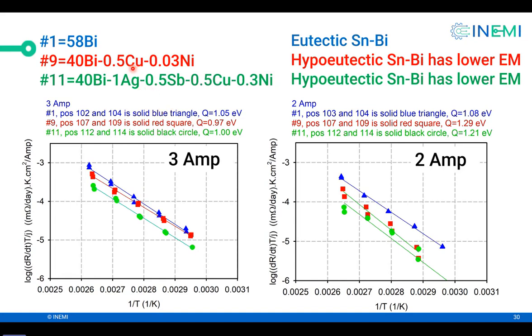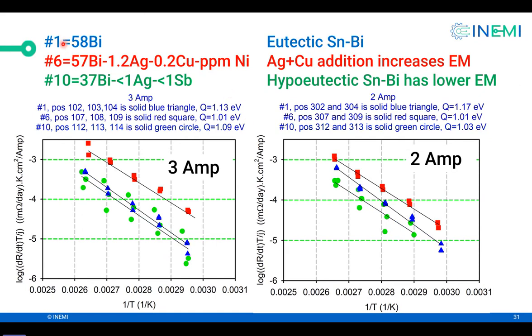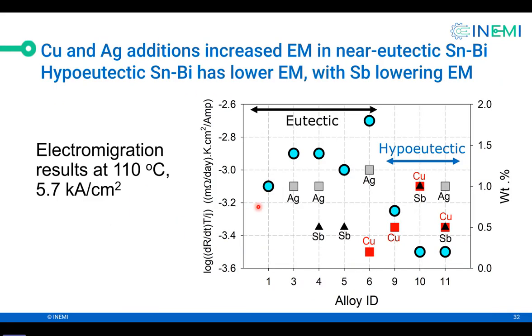And the last set of data is for, again, the eutectic compared to near eutectic with a lot of silver and copper, and the last one is hypoeutectic. You can see hypoeutectic seems to be the lowest, then the eutectic, and then a huge increase in electromigration because of copper silver addition. And then this chart I showed you before is a summary chart, and the bottom line is copper silver additions increase electromigration in near eutectic solder, whereas hypoeutectic has lower electromigration, and antimony decreases electromigration in hypoeutectic solder even further.